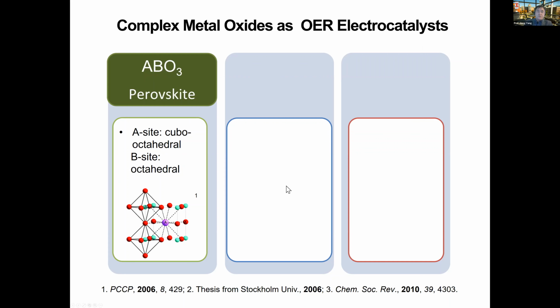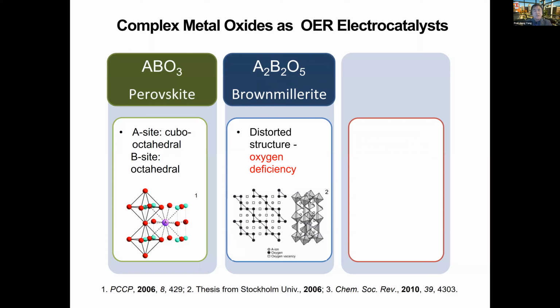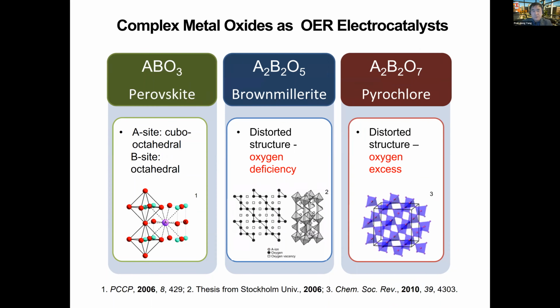So at that moment, I like to think, since this is an oxide, I like to focus on whether we can start to control the oxygen, right? So that could be a quite interesting aspect. So the first thing I was thinking about is, can we start thinking about the oxygen-deficient structure? This will change the valence or the covalency of the structures, as well as potentially the lattice defect or the accessibility of the sites of interest, for example, the B site. So what about the other type? The other defect type of perovskite related to this is the pyrochlore.